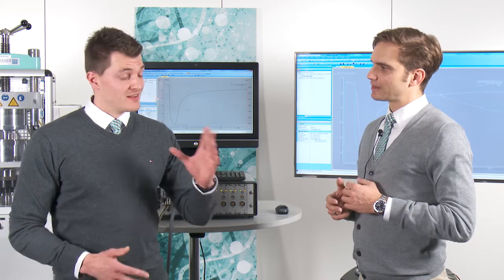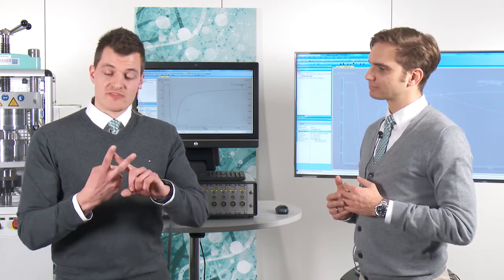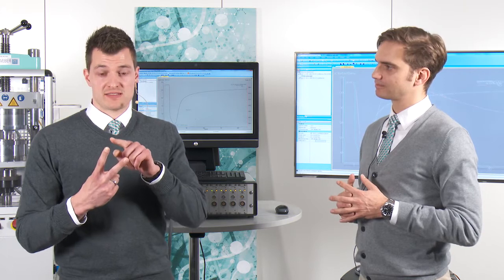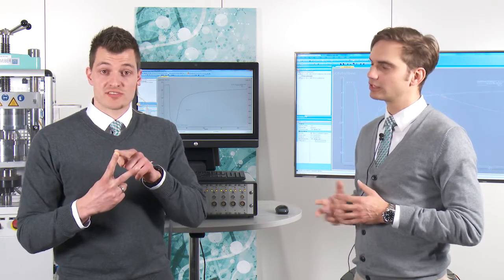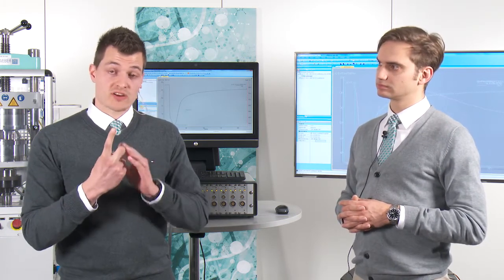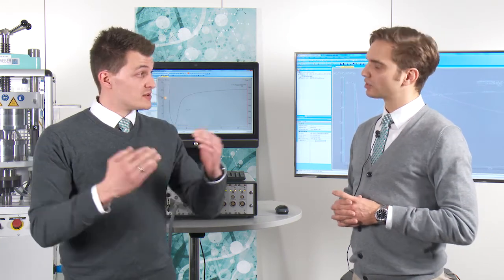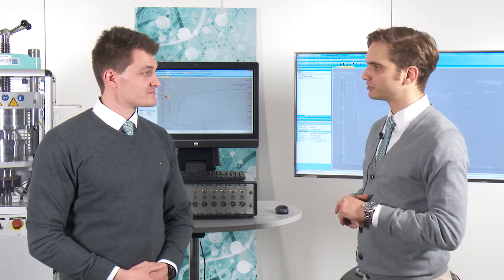Question relating to that already. What about unpolar materials? Regarding the answer for the polyurethane systems, we have two effects we measure. So we measure polarization and the mobility of charge carriers, of ions, of electrons. For unpolar materials, we don't have polarization effects, so we cannot measure this. But we can measure the mobility of charge carriers and ions that will decrease during the curing process of a material. And if the mobility is decreasing, we can see something in the DEA, so we can also trace these processes.